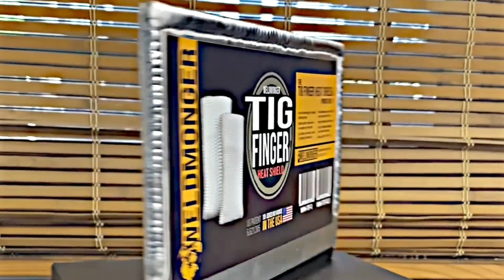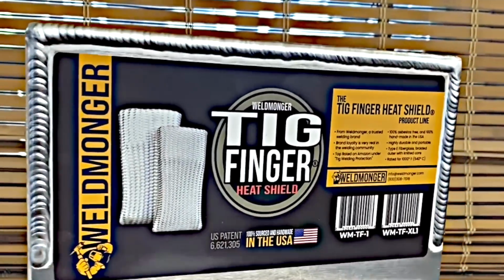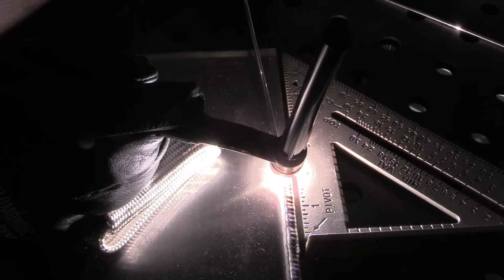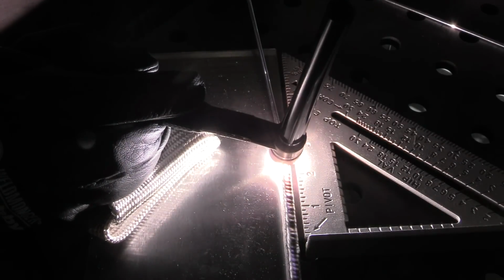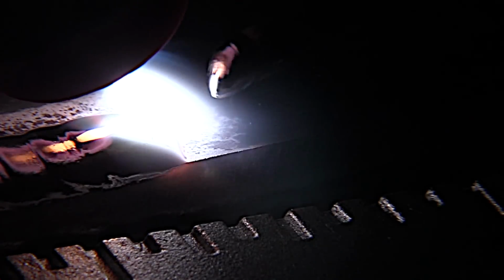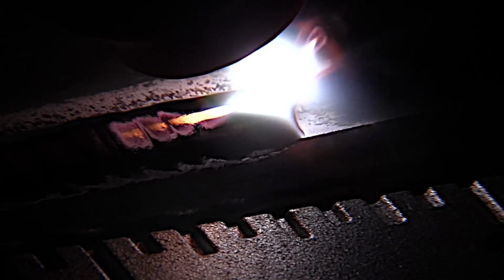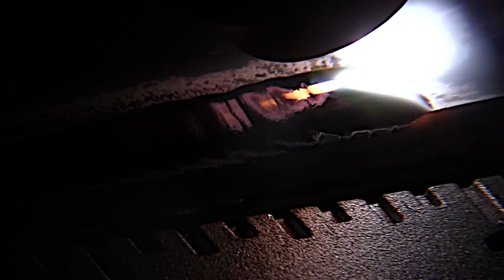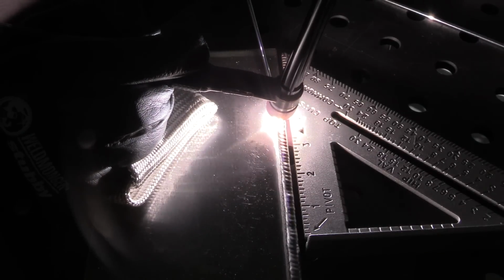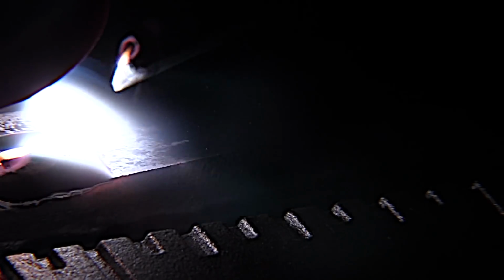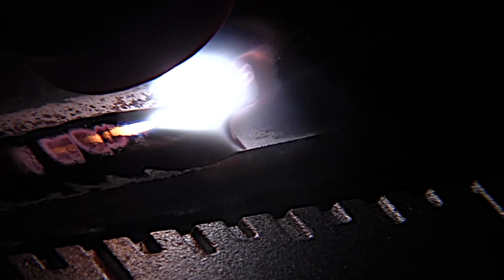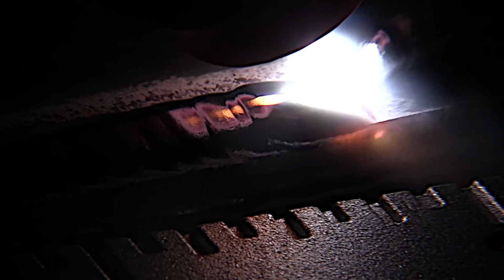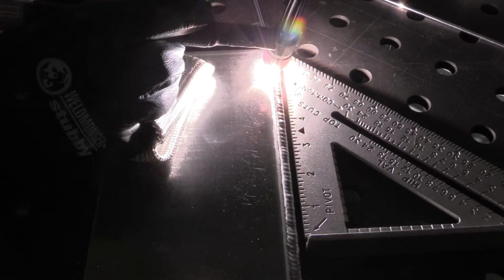Let's get back to that placard though. I wound up settling in on that faster travel speed. Found that the beads looked every bit as good when I was motoring on at 12 inches a minute than at 7.5 inches a minute. Since I was using 1/8 4943 filler metal, I didn't have to worry about my filler rod hand keeping up. And because I was using a number 6 gas lens, it kept the tip of that rod shielded really well.